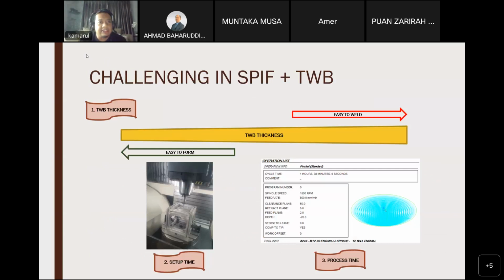Okay, this is challenging during this process when I combine together process SPIF and Tailor Blank. Actually, the challenge starts when providing the sample itself, because when the material thickness is very thin, it's very difficult to weld. It's difficult to weld due to the warpage issue and also defect issues during the process, because friction stir welding also produces high residual stress and heat distribution.